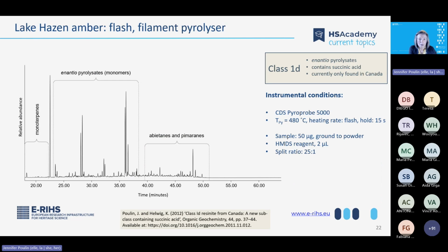Here's what the class 1D amber looked like when it was flash pyrolyzed with the pyroprobe at 480 degrees Celsius. There is a significant peak of succinic acid, and here we can see that there are pairs of enantio pyrolysates. There's 4 of each. There's also monoterpenes, abietanes, and pimaranes present in the amber, and flash pyrolysis here with the pyroprobe gave a really great picture of the building blocks for this amber. Kate and I published it, and it was great. I was really happy, and then I got the TSP.